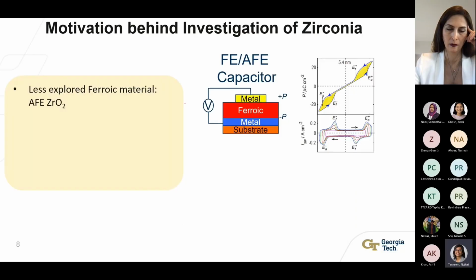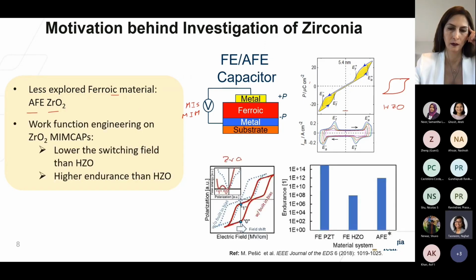As I've mentioned before, in my earlier works I used to fabricate MIS and MIM capacitors, which are metal insulator semiconductor and metal insulator metal capacitors, very great devices if we want to investigate the properties of the deposited materials. Initially, my studies mostly focused on the less explored ferroic material, zirconium oxide, which shows anti-ferroelectricity. This means that it shows a double hysteretic loop in its charge-voltage characteristics instead of the more typical single hysteretic PV loop seen in its more popular counterpart, hafnium zirconium oxide. Some earlier reports showed that these zirconium oxide MIM caps can be made non-volatile by using work function engineering, and these devices actually show a lower switching field and even higher endurance than hafnium zirconium oxide. So this was the initial motivation behind investigating zirconium oxide.